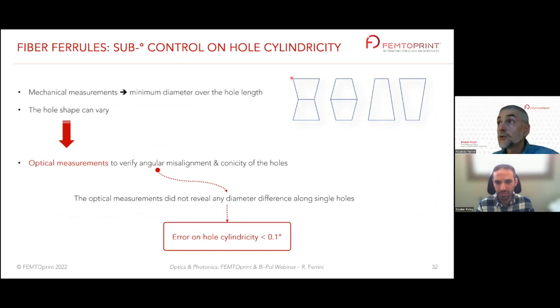We can also control very nicely the shape of the hole inside the hole, in order to avoid, for example, this hourglass effect that would be detrimental because the fiber can enter, but it will stop in the middle. So we have control on the cylindricity of the holes inside the entire hole, which is better than 0.1 degrees.